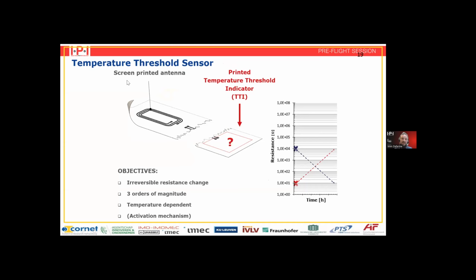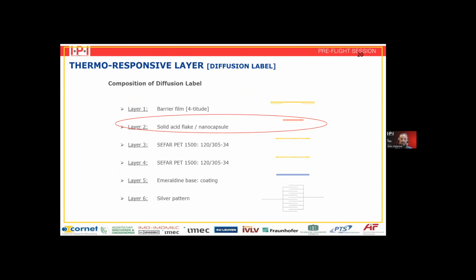So for this temperature threshold sensor, we used the antenna design that we had from screen printing. And then here, this printed temperature threshold indicator using the ultrasonic spray coater to deposit this emeraldine coating. And then looking at a specific resistance change and see if we can sense that with the antenna system and read it out. So what we tried to do is to make a complete stack where you have this interdigit structure, which is screen printed. Then you have your emeraldine based coating. We have some SEFAR PET foils on top to put the nanocapsules and then a barrier coating.